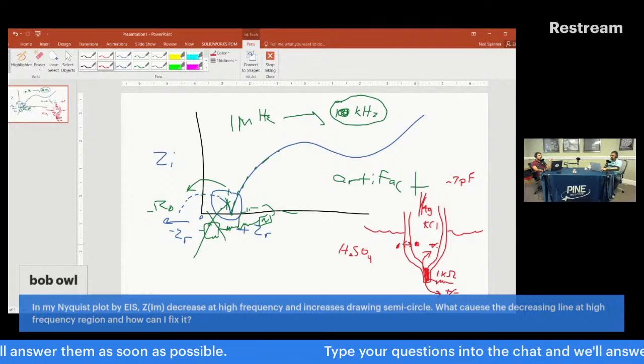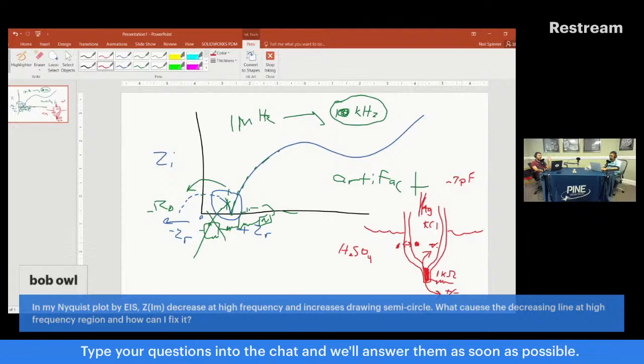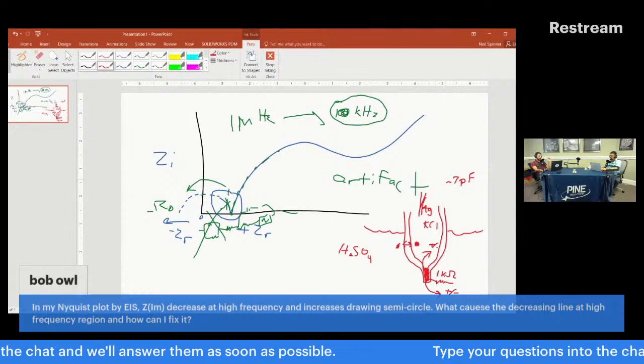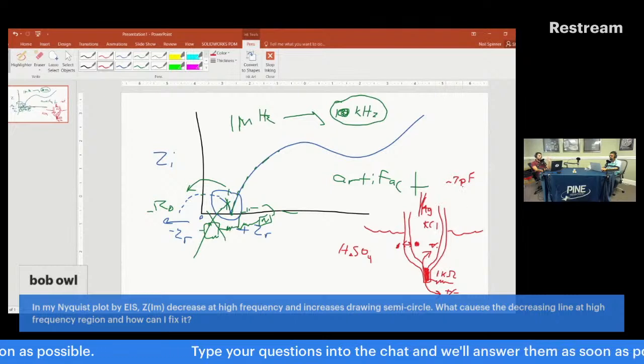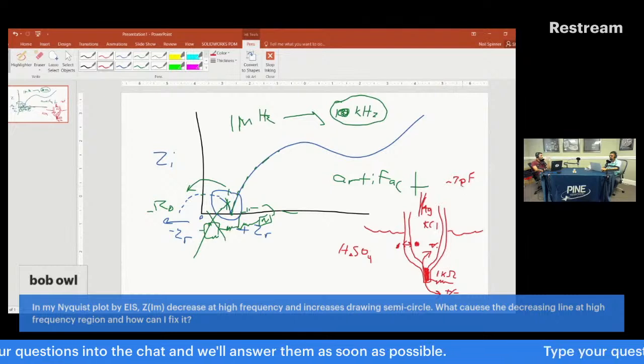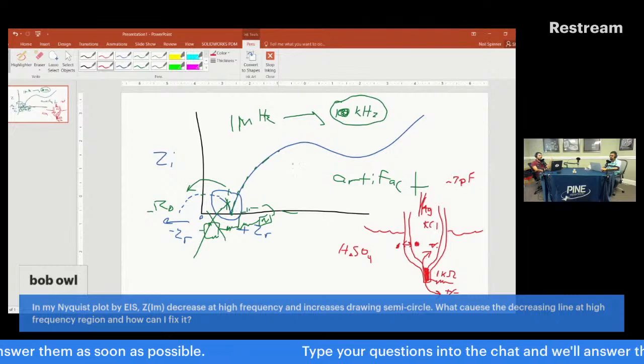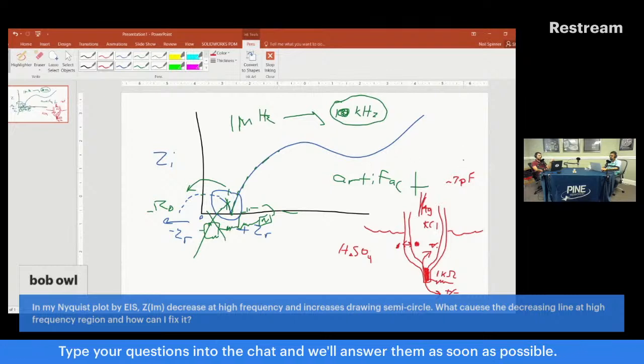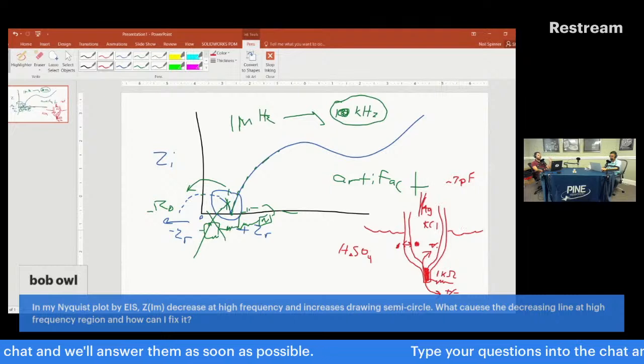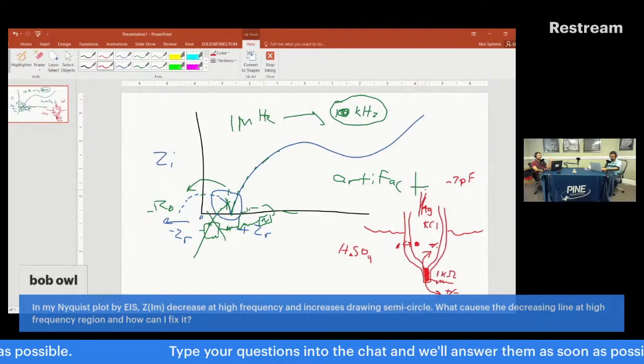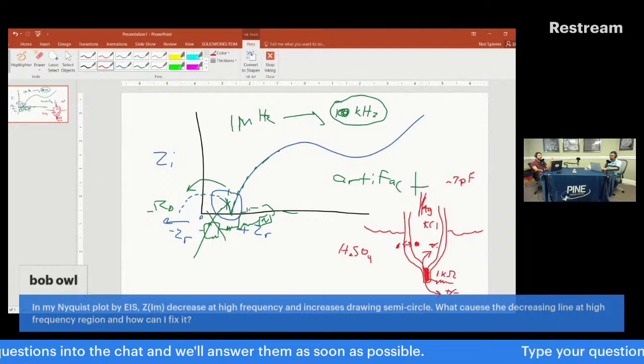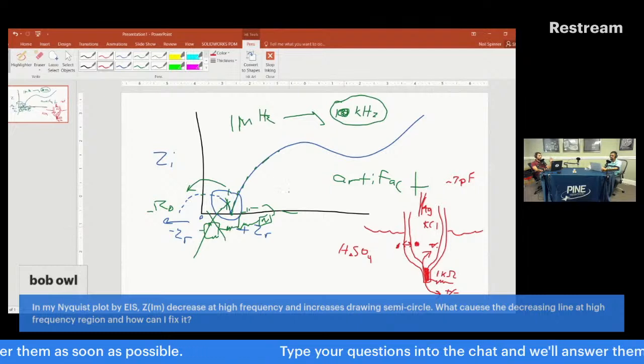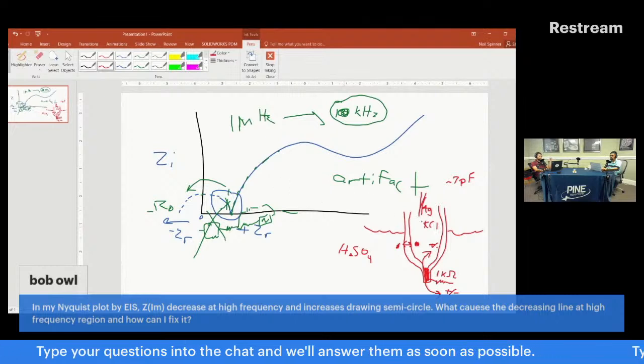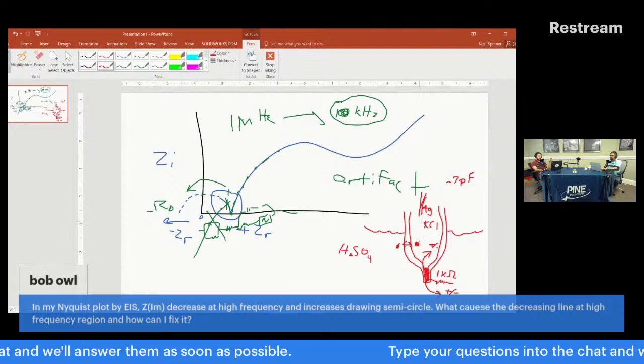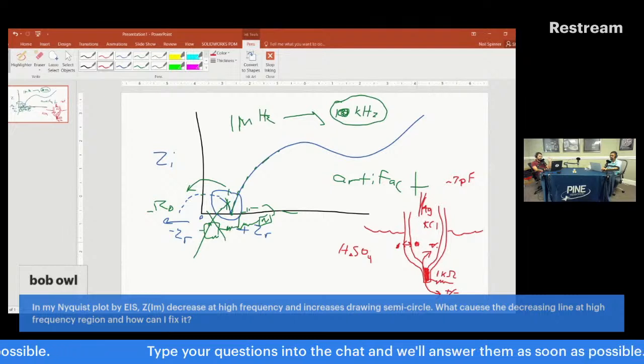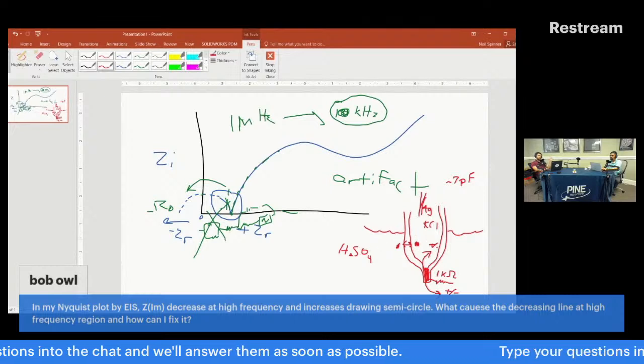Now, this capacitance of about 7 picofarads, if you do the math on this, basically at a high frequency, a resistor does not change its impedance, but a capacitor has a low impedance at high frequency. And so this goes back to this artifact problem. At about 1 megahertz, the impedance of a picofarad capacitor can drop below 1 kilo ohm. So at very high frequencies, what's actually happening is your potentiostat is following the path of least resistance, which in this case means that it is sensing through the AgCl wire and then through the glass. There's just nothing good about that. It's bad, but it's the lowest resistance pathway to sense at that frequency. At that frequency, it is preferred impedance-wise to sense through the capacitor, through the glassware, for a few short frequencies.